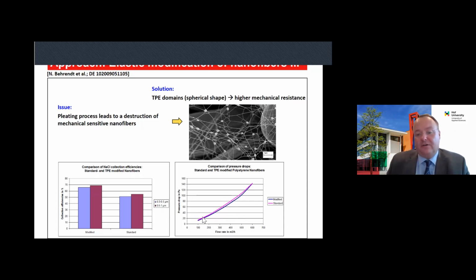And here you can see a comparison of the modified and the standard material. There is no big difference. It seems that the modified material is a little bit better, because the pressure drop is lower. However, it's within the frame of the measurement error, and therefore I would say it's nearly the same. So that's one approach.